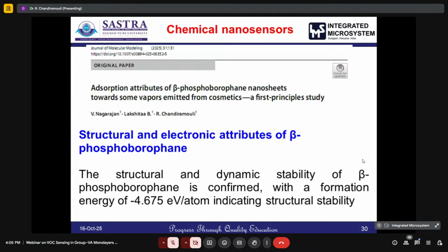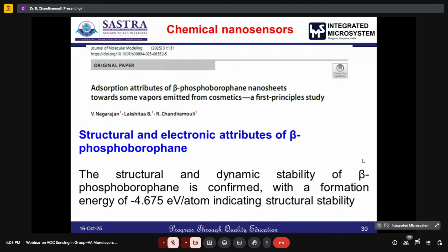Phosphorene is a group 5A material, and here we used borophene. Borophene is a group 3A material, and if you use phosphoborophane, then that will become metallic. We already executed that, and it shows a metallic property. In order to make it a semiconducting material, we hydrogenated the beta phosphoborophane vertically, so that the band gap can be opened, so that it can be suitable for the chemical nanosensor.